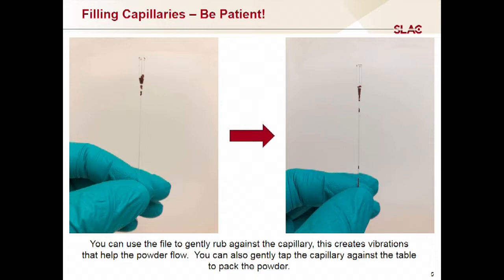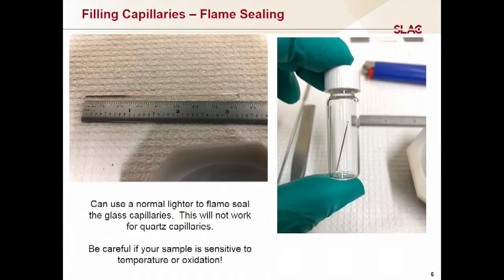And so once you have that, what I'm showing here, it's probably difficult to see. This is the end of the funnel here. You may see that some of the powder kind of stuck to the wall of the capillary, so it looks a little bit pink. Down here is the packed powder bed, and I've got almost an inch of packed capillary there, which is going to be plenty.